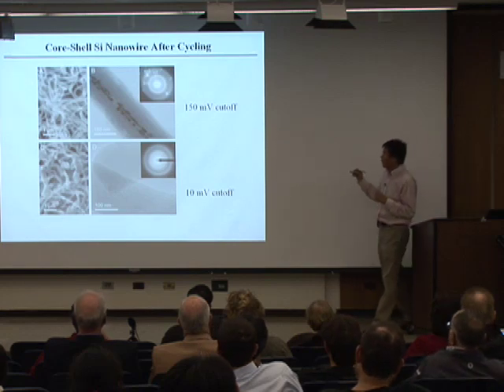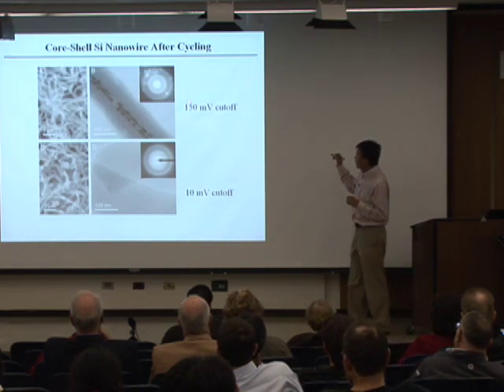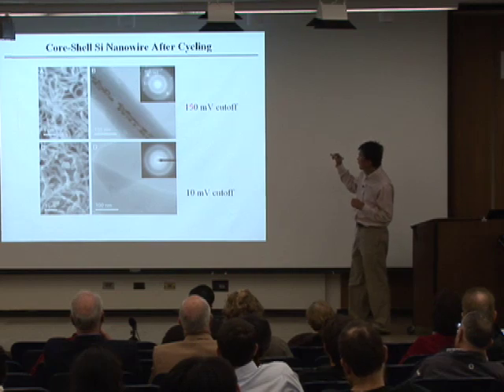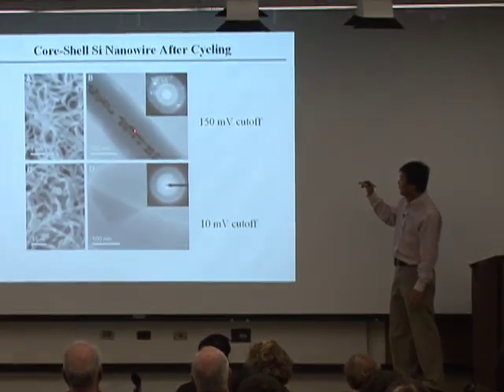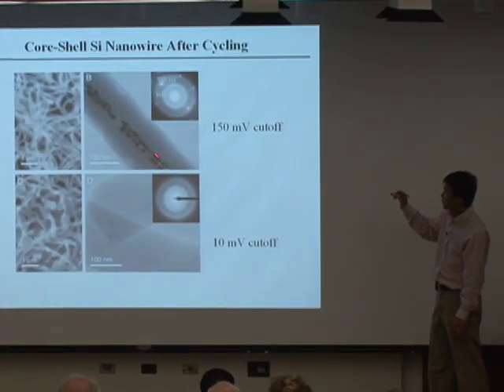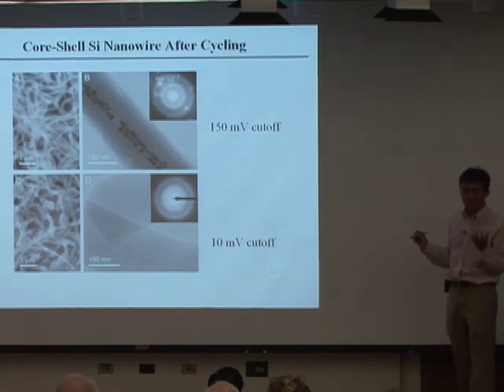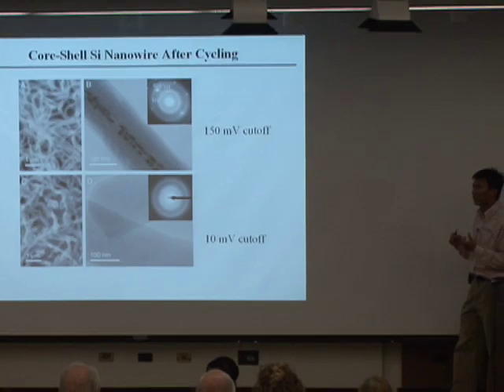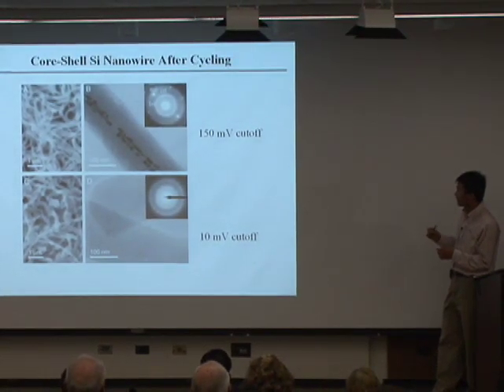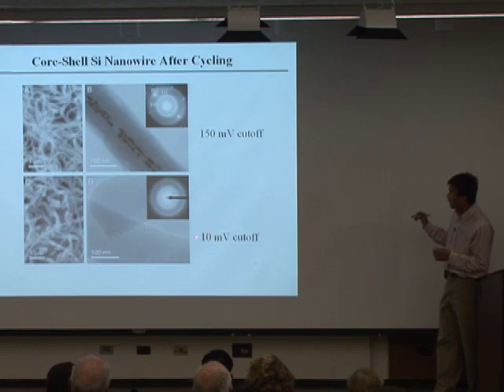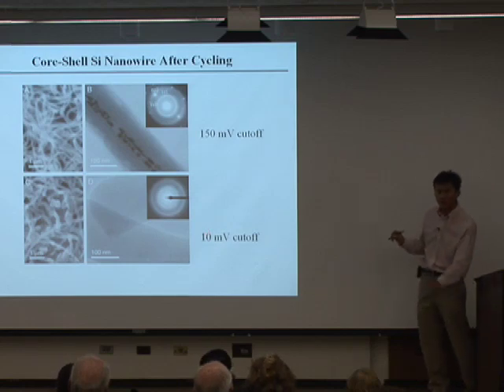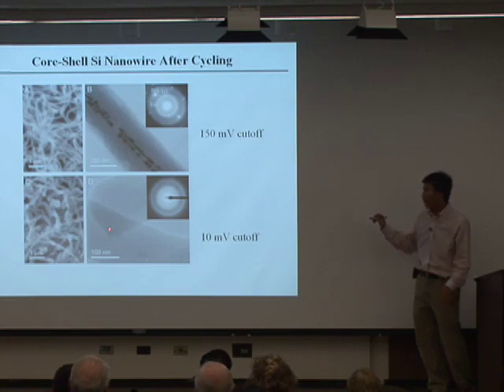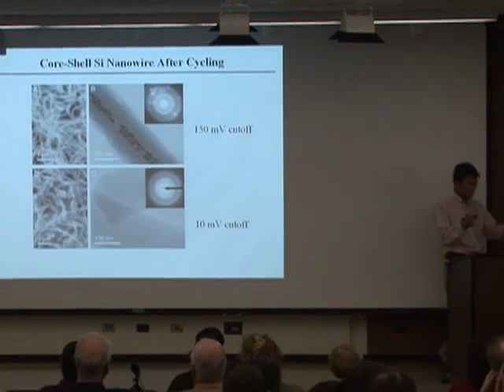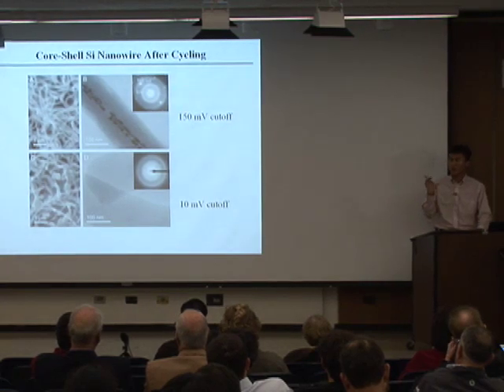So to compare, if you limit the charging potential to about 150 millivolts, you don't go below that. After tens of cycles, you can see this crystalline core still inside. So it is maintained as a mechanical support and electrical support to allow you to do extremely fast charging and discharging. And if you charge your battery with this core-shell nanowire using a very low potential, after you charge it once, the whole nanowire becomes amorphous. You don't see this crystalline core anymore. Well, that is consistent with our ideas. We can maintain this crystalline core by limiting the charging potential.